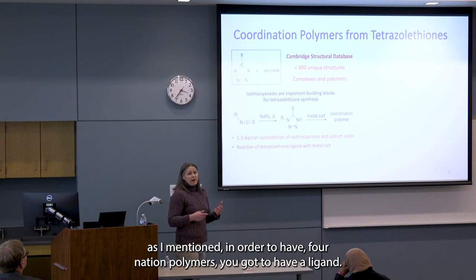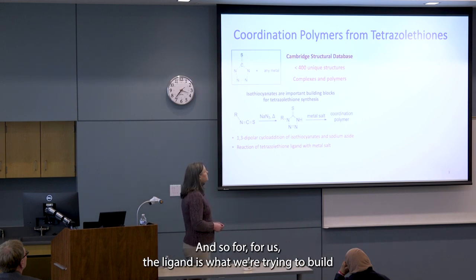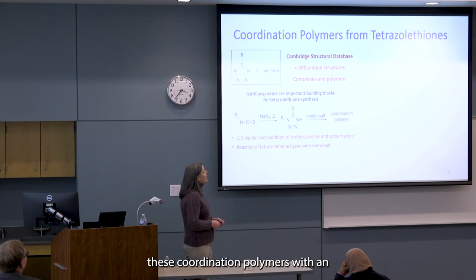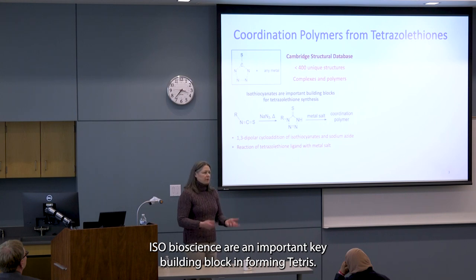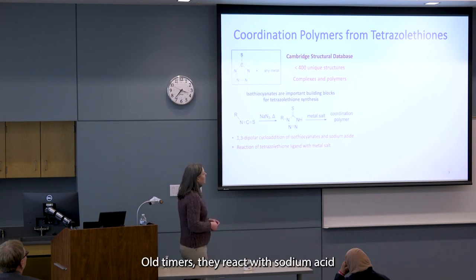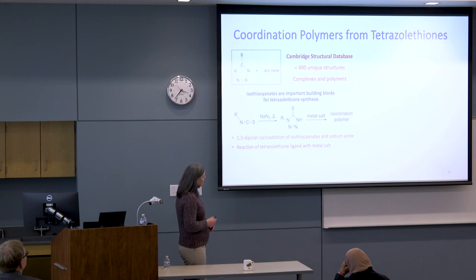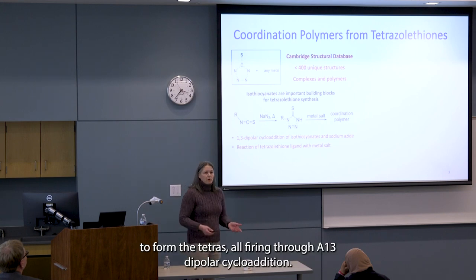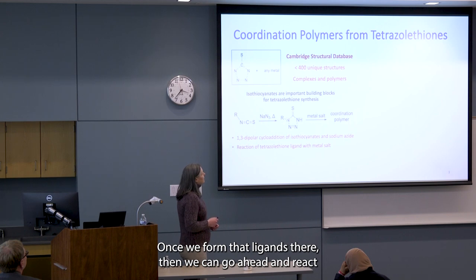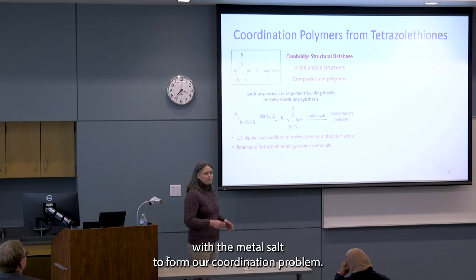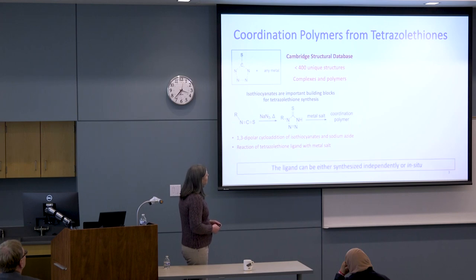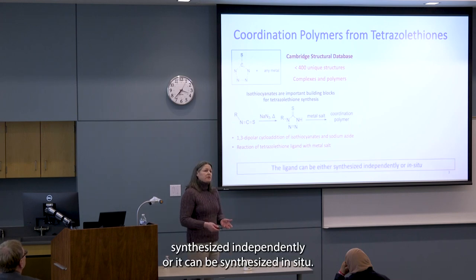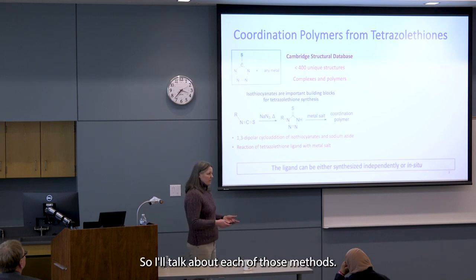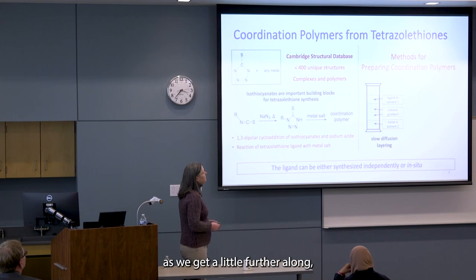As I mentioned, in order to have a coordination polymer, you've got to have a ligand. And so for us, the tetrazolthione ligand is what we're trying to build these coordination polymers with. And isothiocyanates are an important key building block in forming tetrazolthiones. They react with sodium azide to form the tetrazolthione ring through a 1,3 dipolar cycloaddition. Once we form that ligand, then we can go ahead and react it with the metal salt to form our coordination polymer. The ligand itself can be either synthesized independently, or it can be synthesized in situ. So I'll talk about each of those methods as we get a little further along.